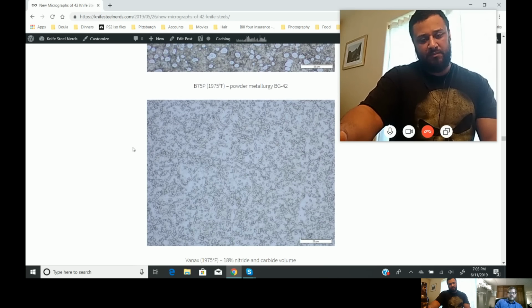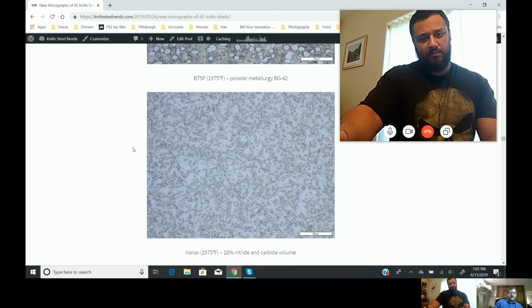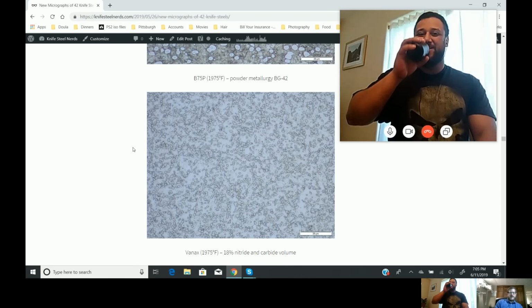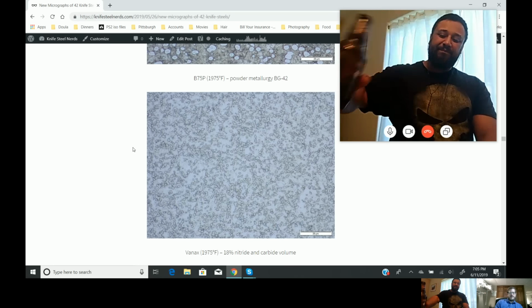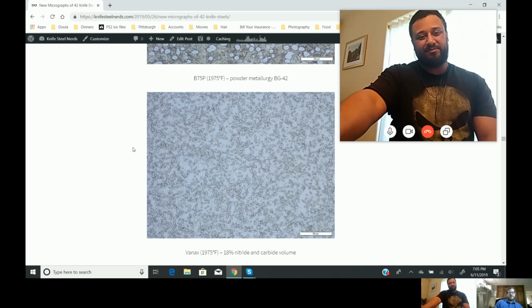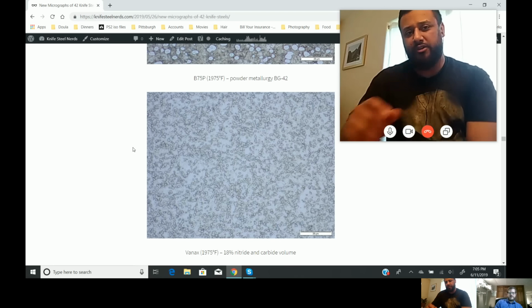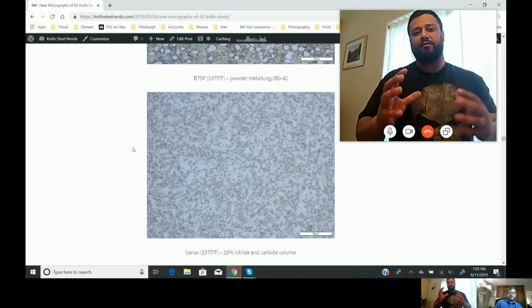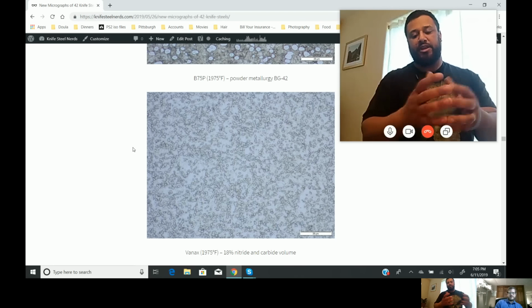So here's Vanax, which is a high nitrogen vanadium alloyed steel. And boy, is it fine. Yeah, this one's really fine. And this is because of the process by which it is produced, where they nitride the powder after it's been atomized. So the nitrides form at a lower temperature than the carbides, and that keeps them finer. Which was really interesting because I was thinking it was just a product of it being nitrogen.